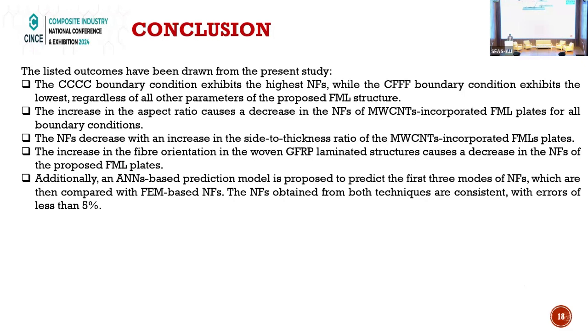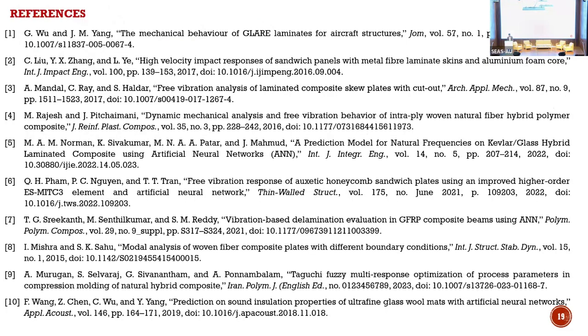Additionally, an ANN based prediction model is proposed to predict the first 3 modes of natural frequency, which are then compared with the FEM based software, and the natural frequencies obtained from both techniques, the finite element method and the data driven artificial neural network, have less than 5% error. Thank you.